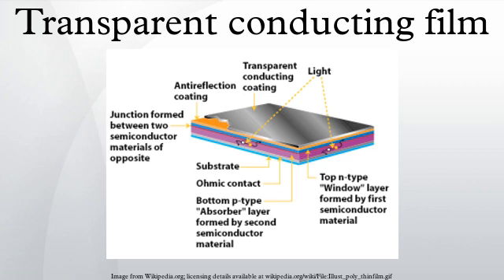Doping PEDOT with poly(styrene sulfonate), PSS, can improve properties over unmodified PEDOT. This PEDOT:PSS compound has become the industry leader in transparent conductive polymers. PEDOT:PSS is water soluble, making processing easier. PEDOT:PSS has a conductivity ranging from 400 to 600 S/cm while still transmitting 80% of visible light.